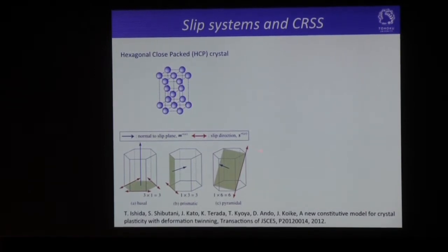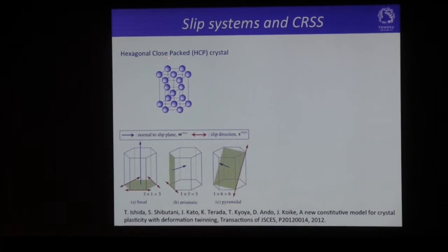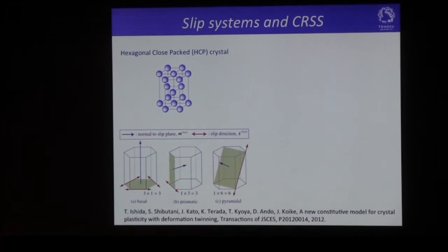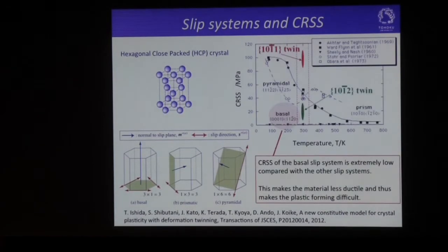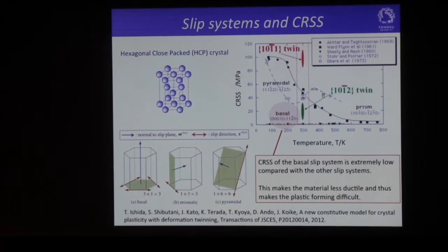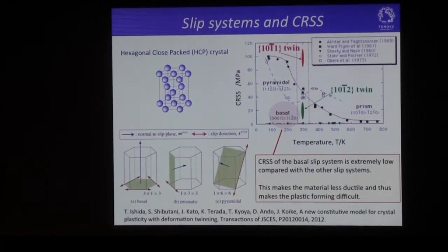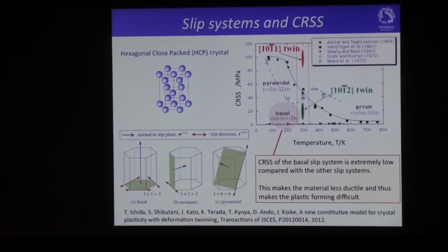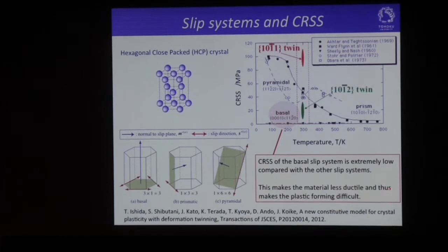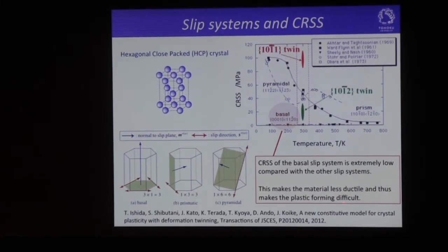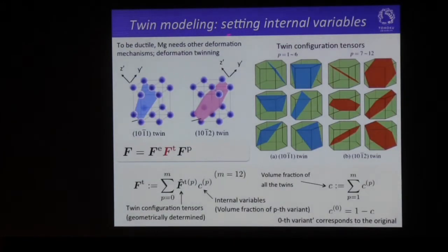That is, these are the slip systems of the hexagonal close-packed crystal of magnesium. The very important feature of this material is that the critical resolved shear stress of the basal slip here is extremely low compared with the other slip systems like here. So this feature makes the material less ductile and thus makes plastic forming very difficult. So in order to be more ductile, the magnesium should have other deformation mechanisms. One of them must be deformation twinning, like this.